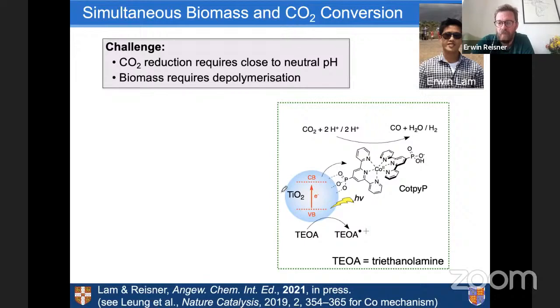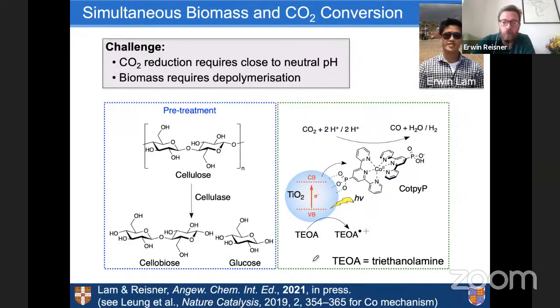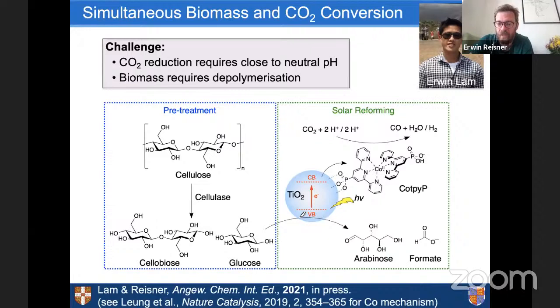So he showed that this system works under sacrificial conditions first with triethanolamine. Then the question was how to replace this triethanolamine by biomass. And here, in fact, we use quite a simple trick. We just use cellulose. We knew we have to be at neutral pH, and that's fantastic for biology. So we just take some cellulases, enzymes that can depolymerize cellulose. These break this down to cellobiose and glucose. And now we can just feed this to the titanium dioxide and convert the substrates to arabinose, and in particular formate in this case.